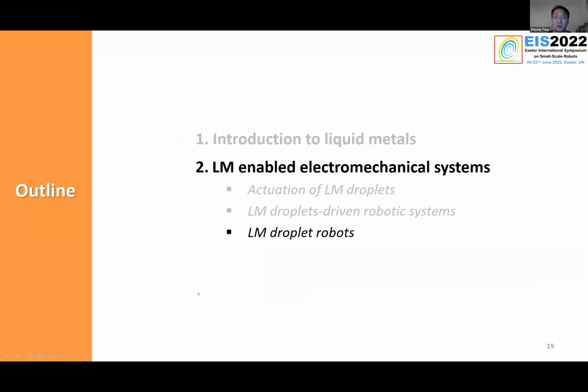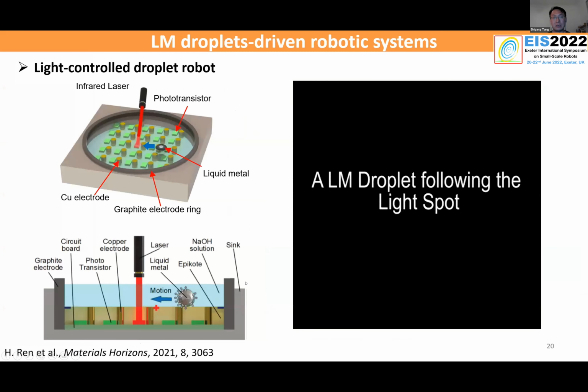Finally, I'll briefly talk about liquid metal droplets themselves as robotic systems. In this case, we created arrays of electrodes which are controlled by phototransistors, and in the surroundings we made a circular shaped graphite electrode. Upon activating individual phototransistors, we're able to activate the corresponding electrode, thereby attracting the droplet towards the activated electrode, and the active electrodes are acting as anode.